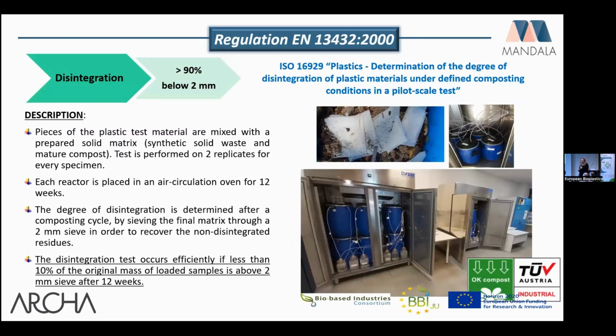For the disintegration test, we performed the test according to another standard that is important to use to assure that our materials are compliant with the requirements. So we applied the ISO 16929 and we used pieces of the film inside the compost in an inoculum, and we followed the test for 12 weeks. At the end, we needed to verify that more than 90% of the initial material is below 2 millimeters in dimension by sieving with a sieve with holes of 2 millimeters. More than 90% is below this sieve.